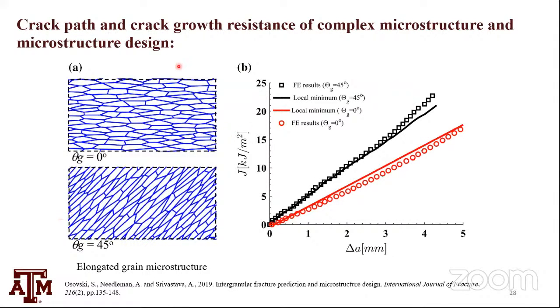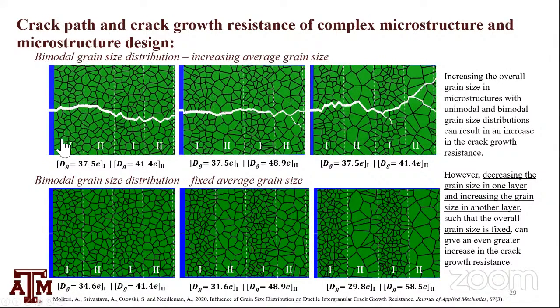I rotated the elongated grain by 45 degrees and showed this nice local minimum, which is what the model predicts, and then these two FE results. It works very nicely, even for very anisotropic grain structures. We have done a lot of them with multimodal grain distributions and show the predictions. So here I have two grain distributions in these layers: smaller grains, larger grains, smaller grains, larger grains. And we get very nice predictions for the whole thing.